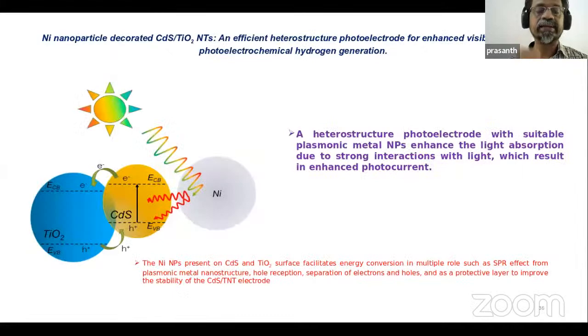And the next is again how to improve the light harvesting of the electrode further. You can make better photocurrent, or you can make better hydrogen production. So we use nickel nanoparticles, that's metallic nanoparticles, that will make a plasmonic effect. It can trap more light into the device structure. So nickel will trap some of the light with the plasmonic effect, and that light can be injected into the CdS system. That will generate an electron hole pair, and that electron hole pair can be injected into the TiO2. That means you are harvesting more light from the solar energy.